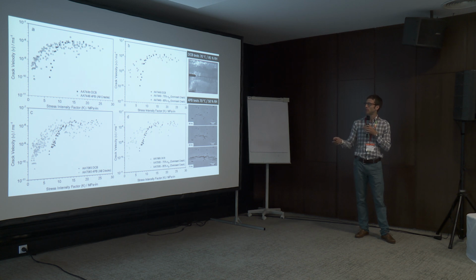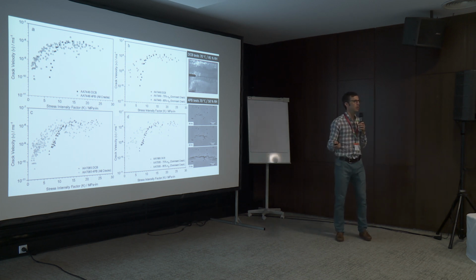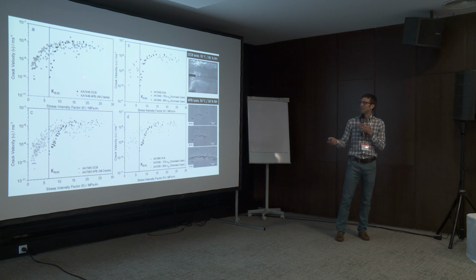Now these large cracks in the DCB are measured through different means, but essentially it's a large crack propagating through the material across many, many grains, a very large crack, and it's coming to an arrest. And it comes to an arrest at this point. What we can see when we have small cracks initiating at a point and growing, and the K going up as they grow, is that they're growing much below this threshold, because previously it was thought this threshold here was establishing the minimum K needed to propagate these cracks. But we've got quite a different scenario when you start from a point compared to starting with this large specimen,